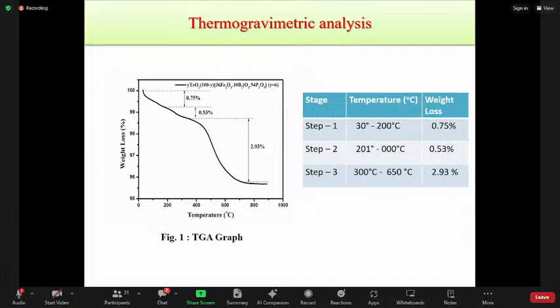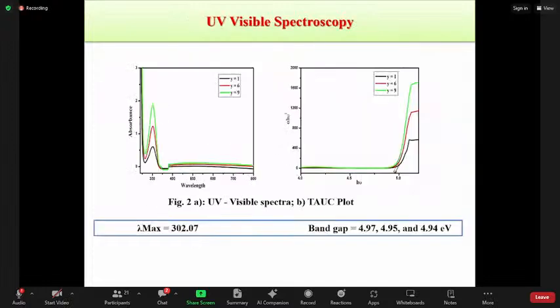Then in the third step, 2.93% weight loss occurs due to the formation of FeO between 300 and 650 degrees, while the 650 to 900 range shows the formation of stable oxides. Then we see the UV visible spectroscopy. In the UV visible spectrum, the maximum absorption peak is observed at 302.07 nanometer.